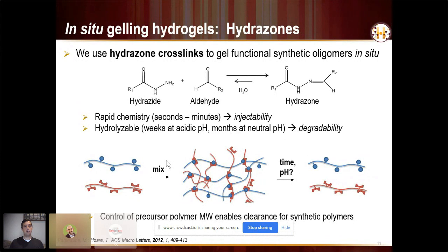So what I've really focused on is the use of hydrazone chemistry to make injectable hydrogels based on these materials. And the reason we like hydrazone chemistry, which is the reaction between a hydrazide and an aldehyde or a ketone group, and I should mention that sometimes we can do this with the H group in the aldehyde replaced with another alkyl group to form a hydrazone bond. This chemistry really has two huge advantages. Number one is we can control the rate at which the crosslinks form, from almost instantaneously to minutes, hours, as we need. So this is perfect for injectability. We can control the gelation rate and thus basically customize or tune it for different applications.